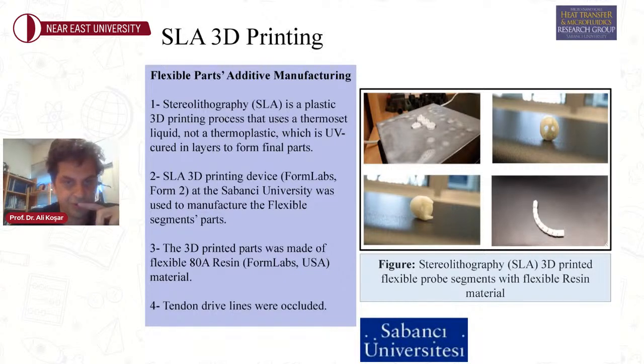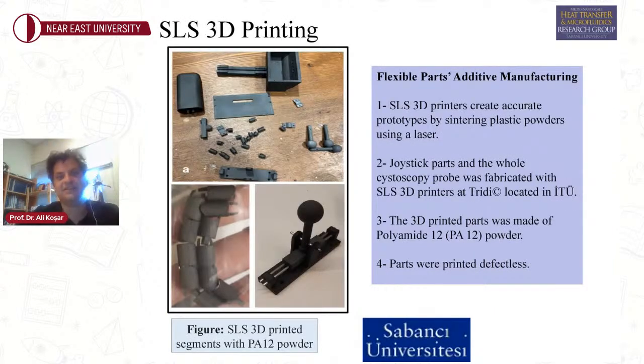So for stereolithography, we could have a resin material version where we could at least make preliminary tests and have an idea about how the system will function. And then we used SLS 3D printing, where we will have a nylon probe, and we use this nylon probe for in vitro tests, and we could also integrate our actuator to this system, and we could both manually and automatically control this and find target using this